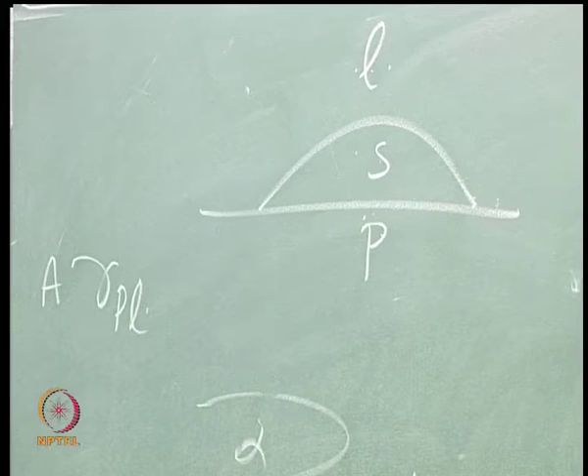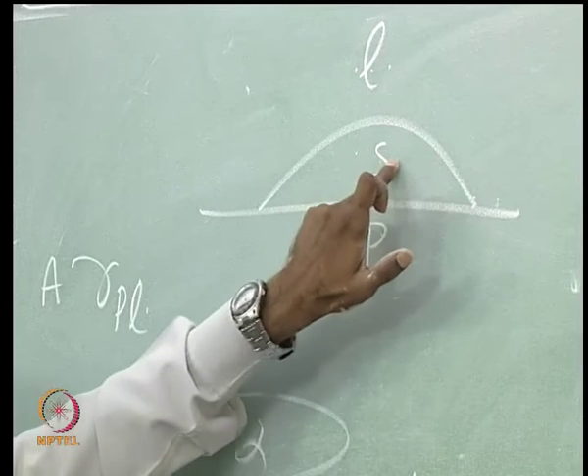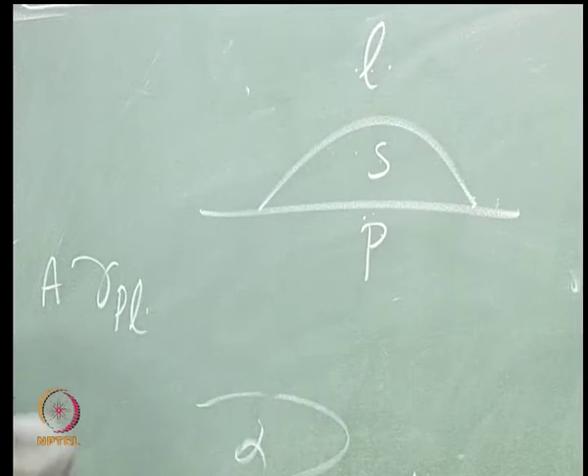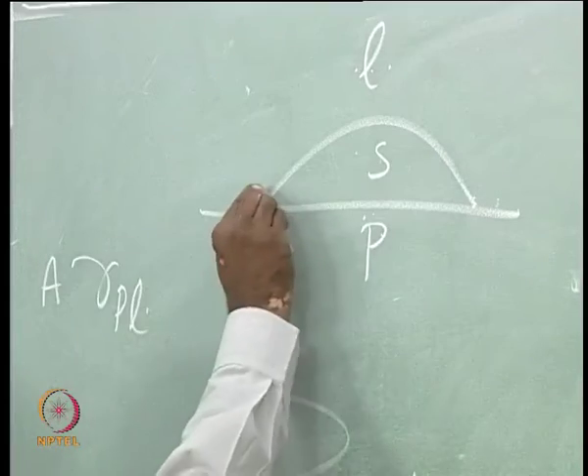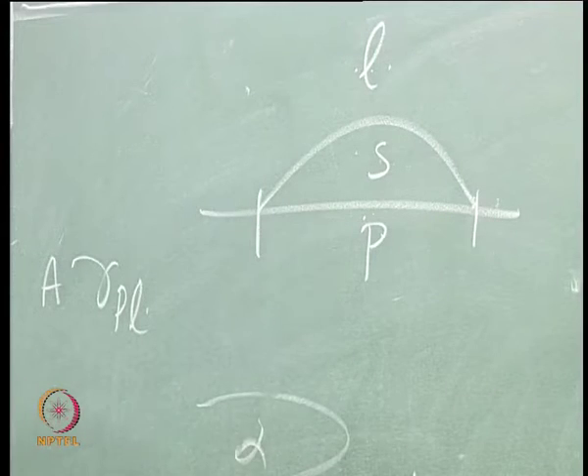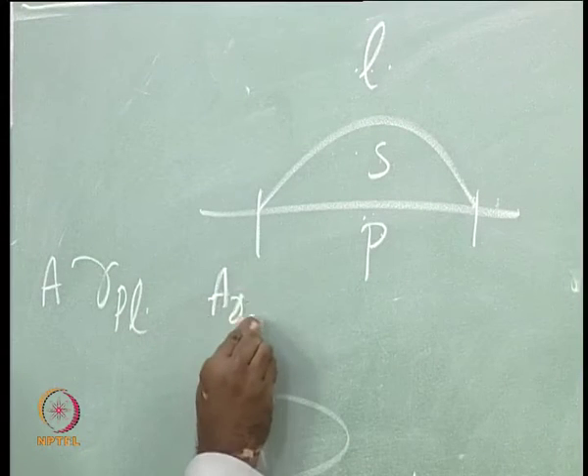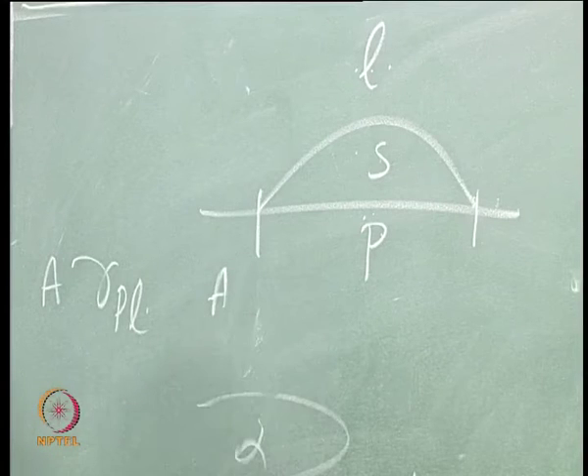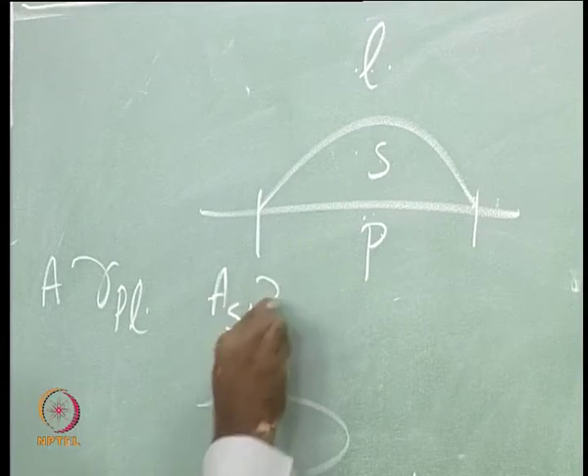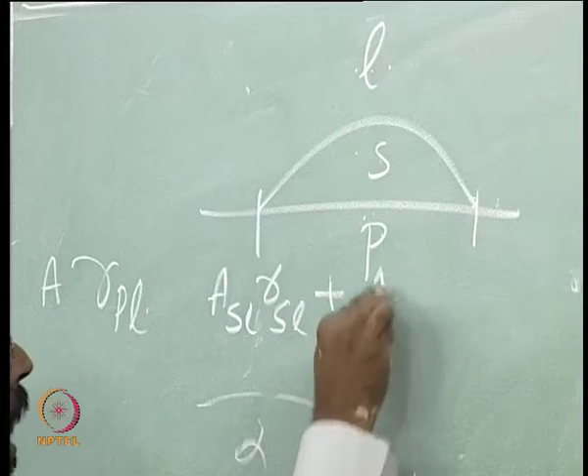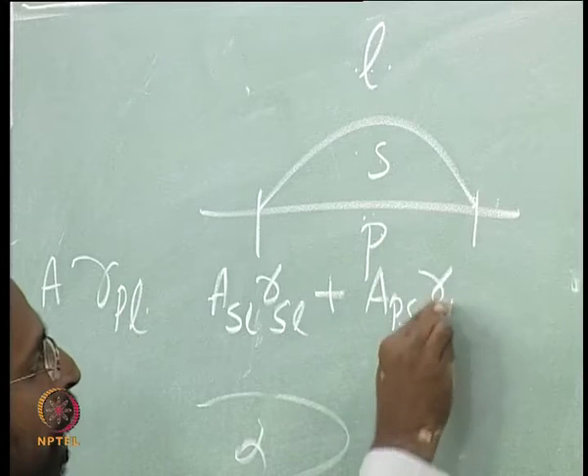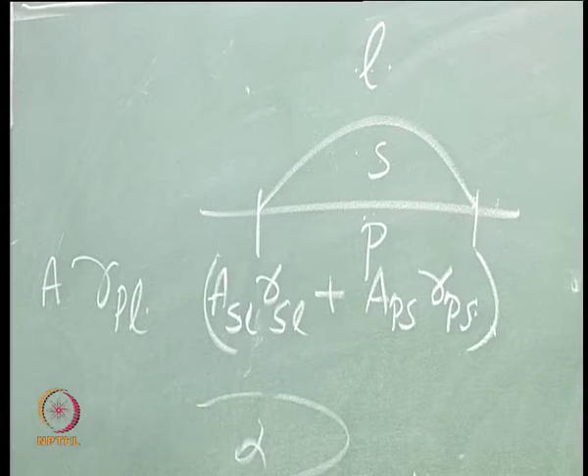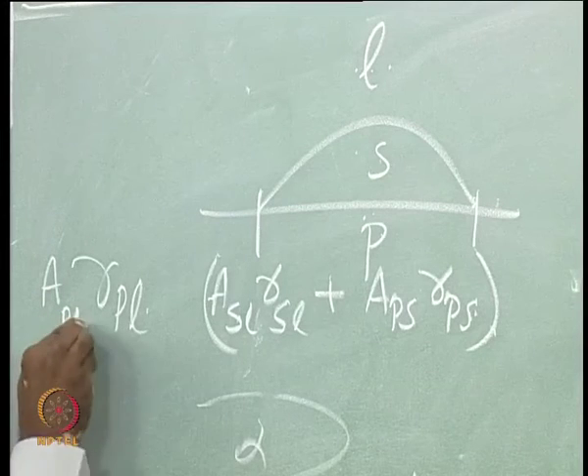Now, the moment a solid nucleates on the particle, you have different interfaces. You have a particle-solid interface, and a solid-liquid interface also. So the particle-liquid interface which was in this area has now been replaced with particle-solid interface and solid-liquid interface. So you will have A of SL into gamma of SL, plus A of PS into gamma of PS.